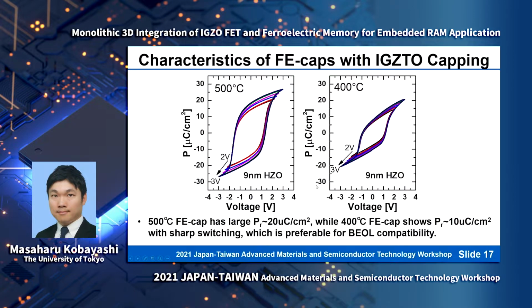Next, we characterize the ferroelectric capacitor with IGZTO capping. From our previous study, if we have IGZO capping on top of the ferroelectric hafnium oxide, we can enlarge the ferroelectricity. So we already published this result using IGZO last year. This time we apply the same technique for IGZTO capping. And again, we were able to obtain very large ferroelectricity and very sharp switching characteristics.